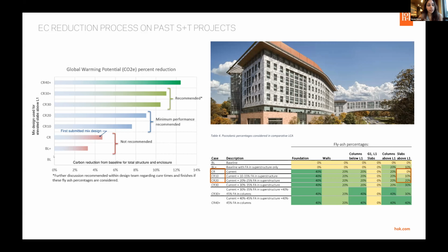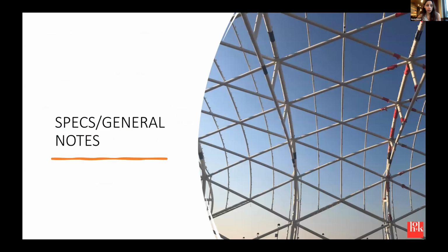So we got from a 0% baseline, 0% fly ash, which is what the contractor had initially wanted to use to keep a very tight construction schedule and get very high early strengths, which structurally we don't need. We designed for 28-day strengths. They wanted those high strengths really early so they could move from floor to floor really quickly. But we found a great happy medium. They were able to make 25% fly ash work. So it just goes to show that doing a life cycle analysis in CA, working with the contractor, can still get you embodied carbon reductions. And they liked being included in that process as well.